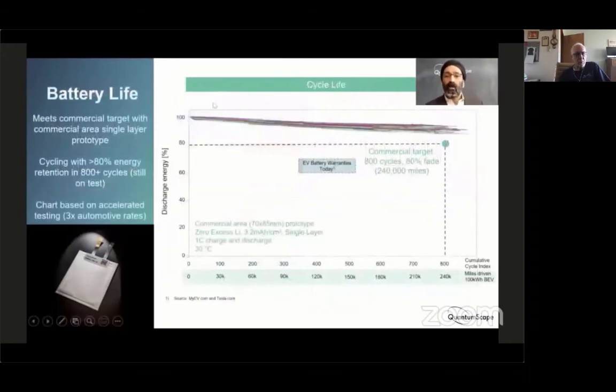And then to assess cycle life, we run our cells under real-world conditions, which represents close to room temperature, so 30 degrees Celsius, 1 C charge and discharge, which is 1 hour charge, 1 hour discharge. Also an aggressive driving condition. Typically, battery cycle life testing is done at slower rates than this, C/3 rates, so 3 hour charge and discharge. There is 0 excess lithium in these cells. These are thick cathodes, over 3 milliamps per centimeter squared, and this is the commercial area of the cell. So these are all real-world conditions. In fact, they're aggressive real-world conditions because of the charge rates and discharge rates.